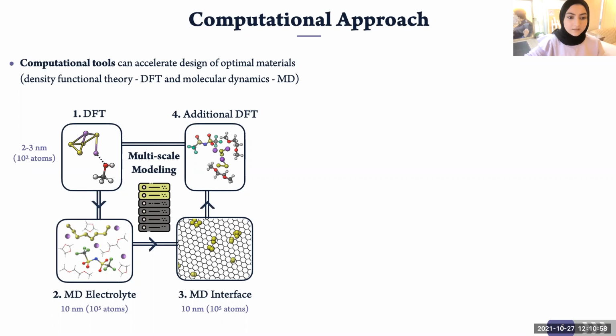And then we use the selected candidates in detailed molecular dynamic simulations, both in the electrolyte and at the cathode interface, in order to study the interactions of these different components in the solution and at the interface as well. And then from these MD simulations, we extract atomic clusters representing the chemical environment of these species of interest, like the salt or the cation, for example, and feed them to additional density functional theory calculations in order to derive more accurate properties rather than just focusing on the individual molecules like in the first step of the process.